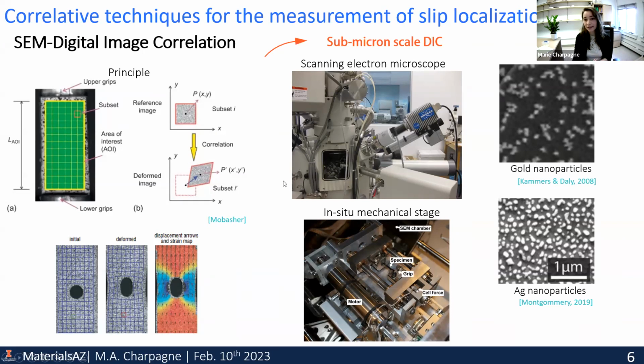But in the scanning electron microscope, we can do a similar approach. The main challenge is to have a smaller speckle, for higher resolution, and also having a stable electron beam so that we can image those particles very well. And this has been developed, as I mentioned, by my colleague JC over the past 10 years. And this is now a technique that works really well. There are several techniques to get those nanoparticles onto the surface. But essentially, the idea of SEM DIC, so DIC collected in the SEM, is that you just miniaturize all the principle of digital image correlation so that you can image much finer features.